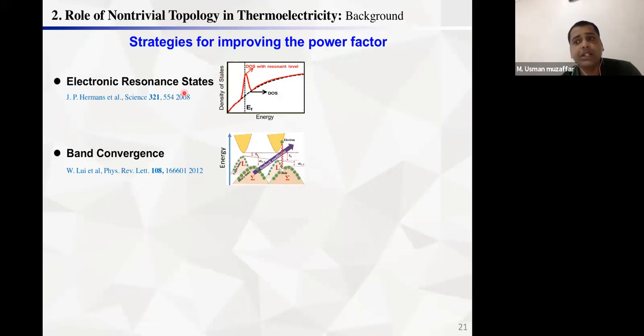The first strategy I used in my papers is the resonant levels. So what are resonant levels? Consider we have a system, assume a PbTe system, a semiconducting system. When we do external doping, I mean the thallium atom at the Pb site, it creates a distortion in the density of states. This is the schematic representation, and you can see this is the undoped density of states, and this is the distortion in the density of states. It's due to the external dopants. The sharper the peak of this distortion, the larger the effective mass and the larger the Seebeck coefficient.